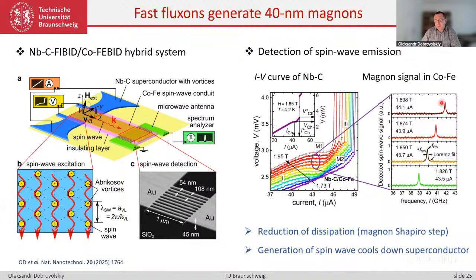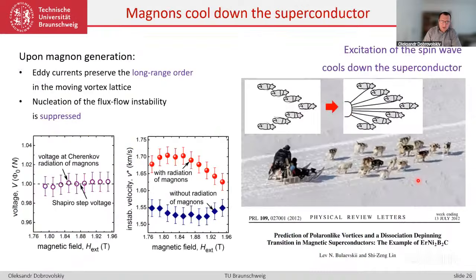And an additional interesting feature is, if we take a look at the frequencies of the generated Magnons and express these voltages from the Shapiro steps as divided by frequency and the number of vortices, knowing the area for the magnetic flux treating the hybrid region, we deduced one magnetic flux quantum. So basically, this Cherenkov resonance threshold condition corresponds to the Josephson relation if one takes into account the number of vortices participating in the Magnon generation. Another interesting feature is that with radiation of Magnons, maximal vortex velocities are now higher because more heat is removed from the superconductor. And this is in line with the prediction of these Polaron-like vortices, where there is a strong interaction of Magnons with Fluxons, whose presence and motion has led to their appearance in the material.